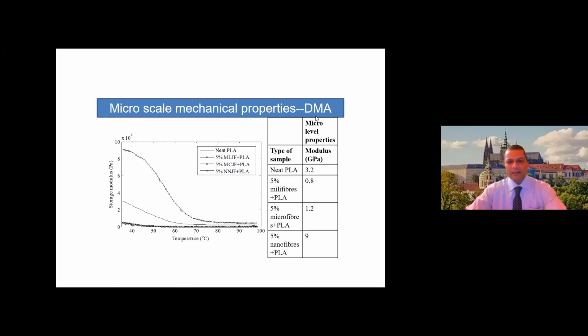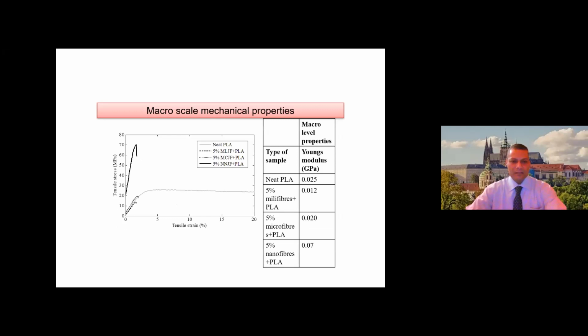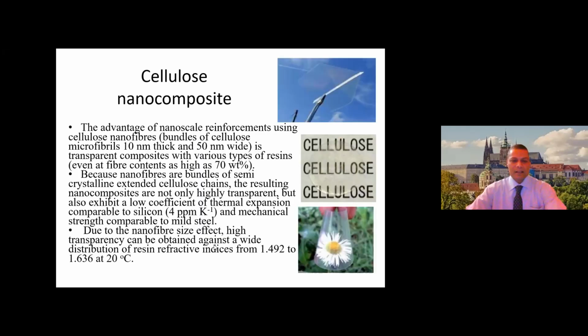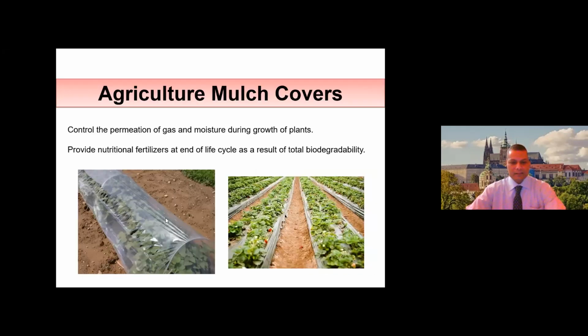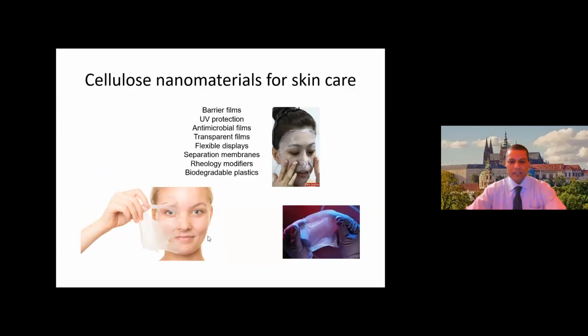Micro level mechanical properties can be analyzed by dynamic mechanical analysis, and the storage modulus was observed to be superior when nanoparticles are added to the polymer film. As such, macro mechanical property by stress strain analysis was also studied. Such nanoparticle-filled composites, known as nanocomposites, are used in the agricultural field, especially for protection of delicate plants from UV light, and the mechanical performance is also superior, so they protect the plants from any kind of damage. At the same time, the interesting feature is they are biodegradable, so it is not a matter of concern that they need to be removed every now and then.